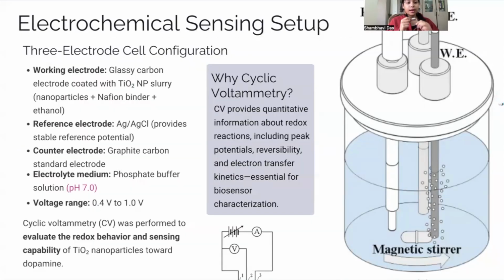Coming to the electrochemical setup, we use cyclic voltammetry to test the redox behavior and sensing capabilities of TiO2 with dopamine. And it was a 3 electrode electrochemical setup, and the working electrode was a glassy carbon electrode coated with TiO2 nanoparticle slurry, which was made of TiO2 nanoparticles, Nafion binder, and ethanol. The reference electrode was an Ag/AgCl electrode, which provides a stable reference potential. And the counter electrode was a graphite carbon standard electrode. The electrolyte medium was a phosphate buffer solution of pH 7, and the voltage range was from about 0.4 volts to 1 volt.